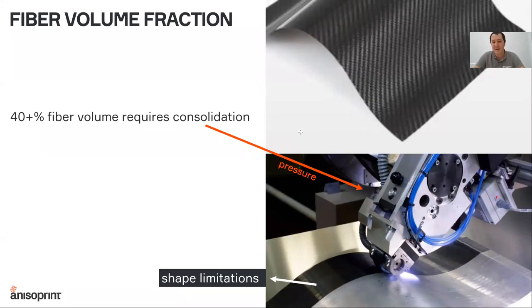But to achieve these high volume fractions of fiber, a high pressure needs to be applied. It is done either by a special roller or by post-consolidation in an autoclave or press. But actually this brings a lot of shape limitations. Basically, by applying pressure, you cannot make 3D structures with complex shapes and thin walls. You will only be able to make flat sheet-like materials. And this is an important part of the co-extrusion.